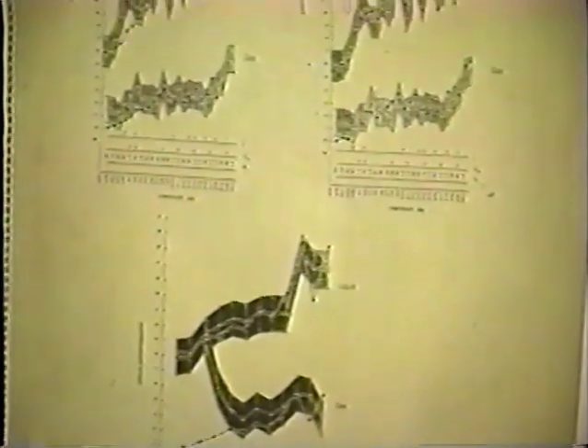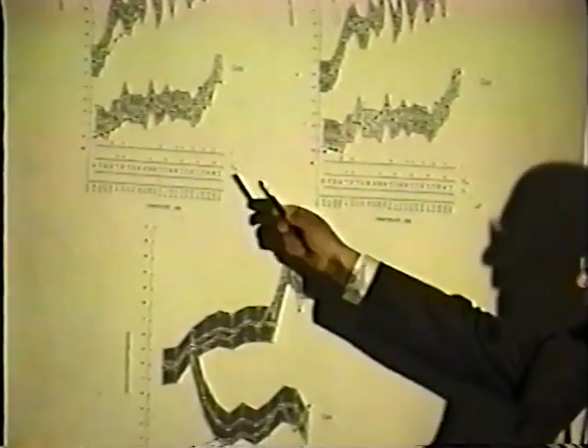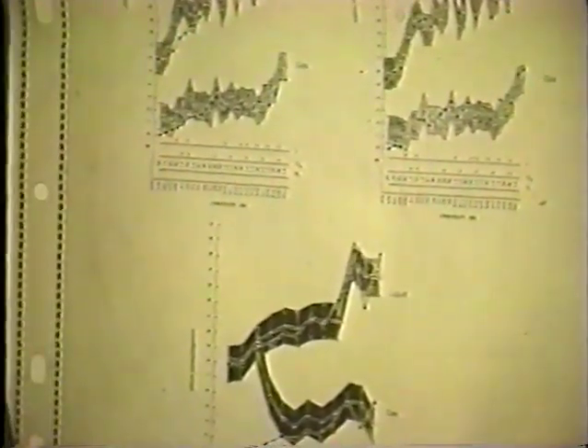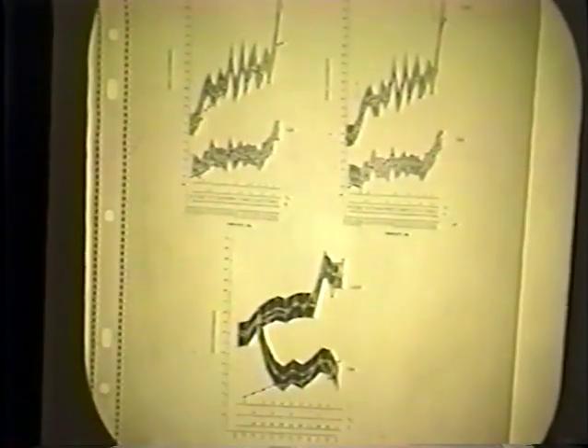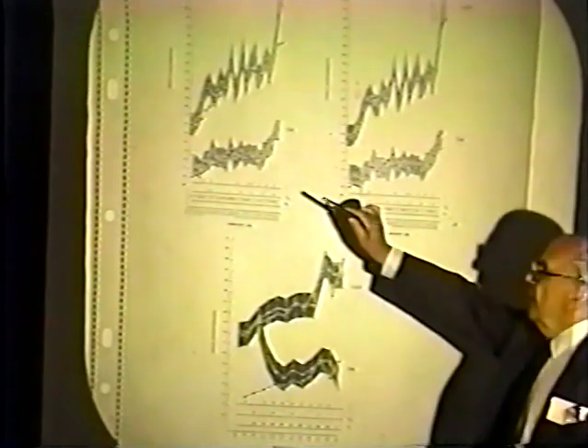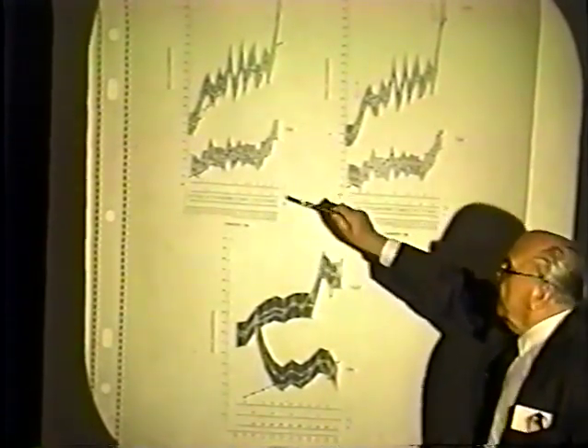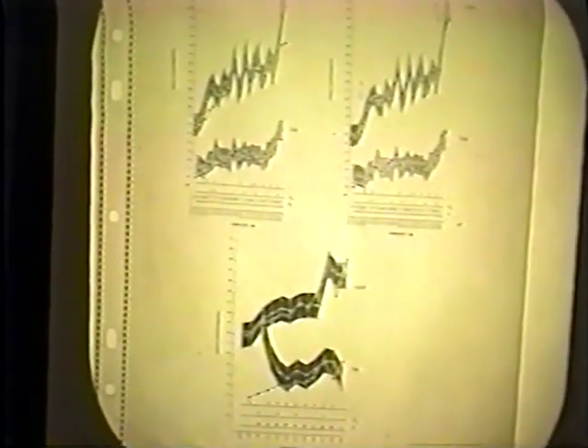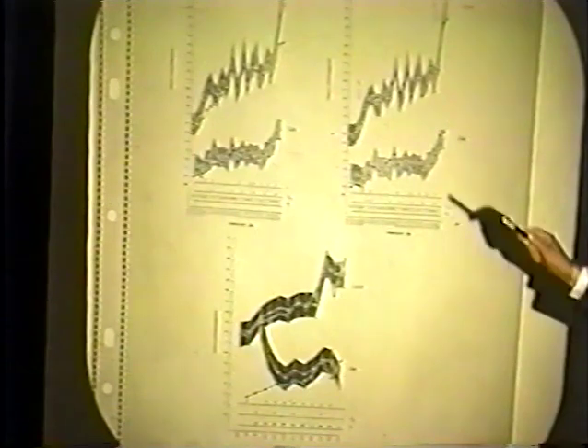They are summarized in here. I'm going to only give you two examples. One in which this has been done on a smooth surface, which is normally obtained by plating at very low current densities, in which you don't have the globules growing. And those are the data as seen. The solid lines are the computed, the open circles are the experimental data.